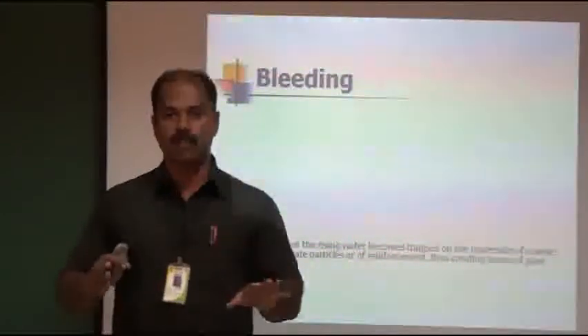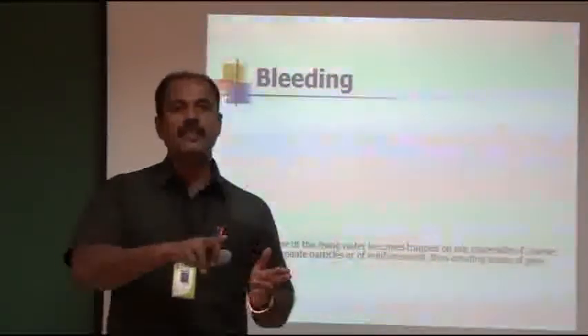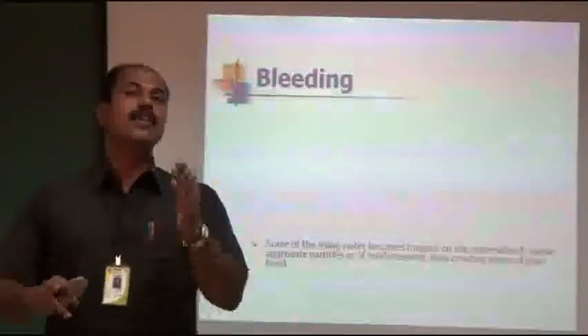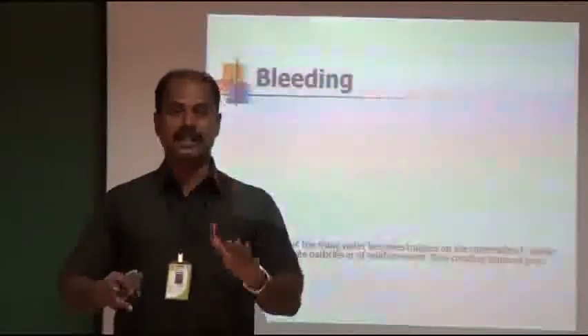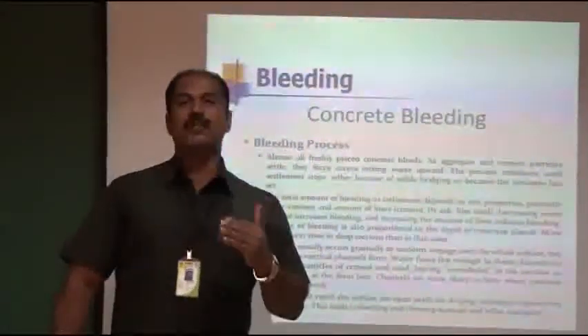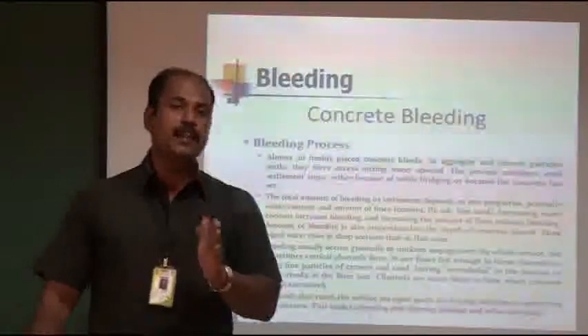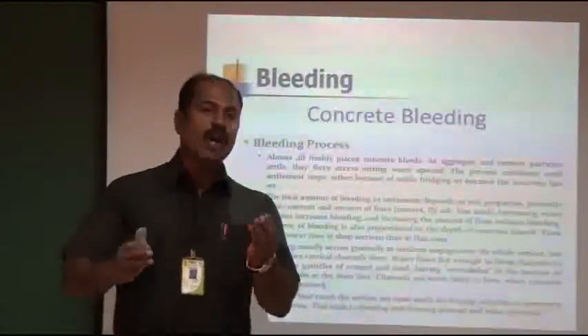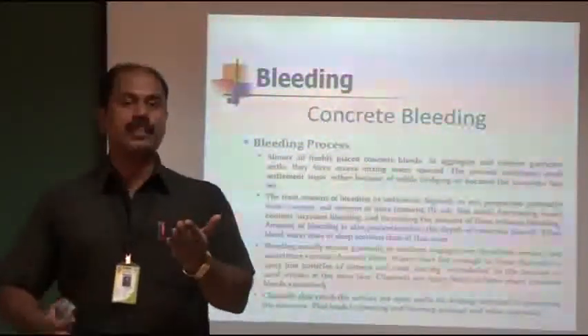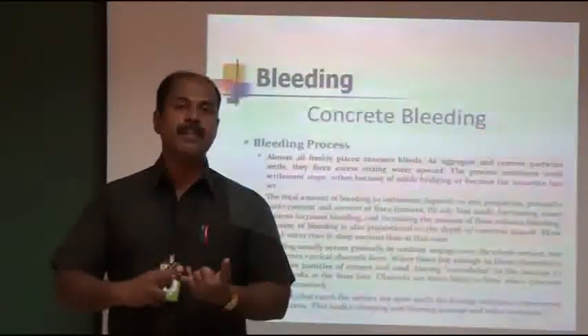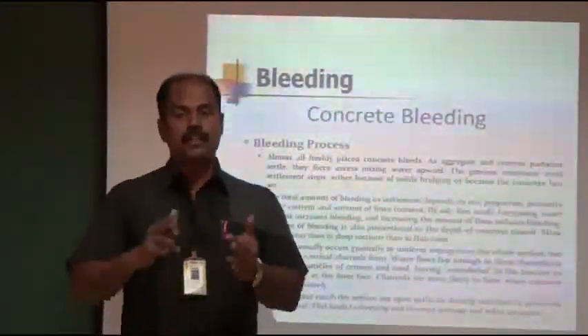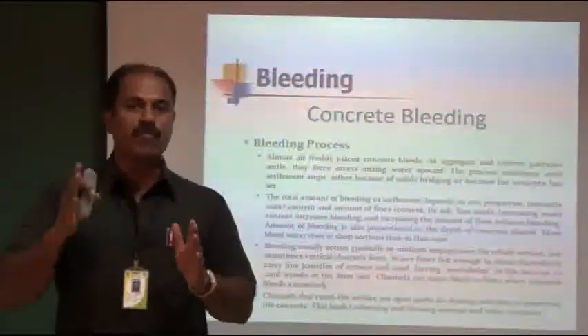Bleeding means excess water collecting on the top surface of the concrete. Segregation means separation of the coarse aggregate from the concrete, but bleeding means the water is repelled onto the top surface of the concrete. That is called bleeding. What are the reasons bleeding occurs? First is a high water cement ratio. If it goes beyond the Indian Standard limit or beyond the mix design limit, water will be repelled onto the top surface of the concrete. Second reason is improper vibration and improper mixing of the concrete. The concrete is mixed with fine, coarse, water and cement.